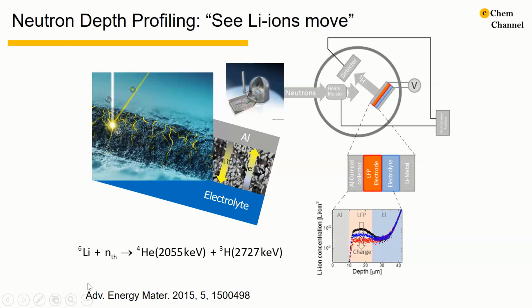When the lithium-6 captures a neutron, it will release a helium nuclei and a tritium. Both elements have very high kinetic energy. Especially the tritium can easily leave the electrode and the cell. After the tritium leaves the electrode, the detector can measure the kinetic energy of the tritium. Then, by comparing the original energy of tritium, we can determine how deep inside our electrode contains lithium, or where the lithium locates in the depth direction.